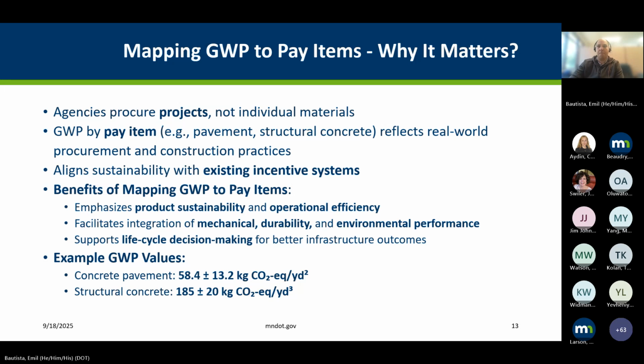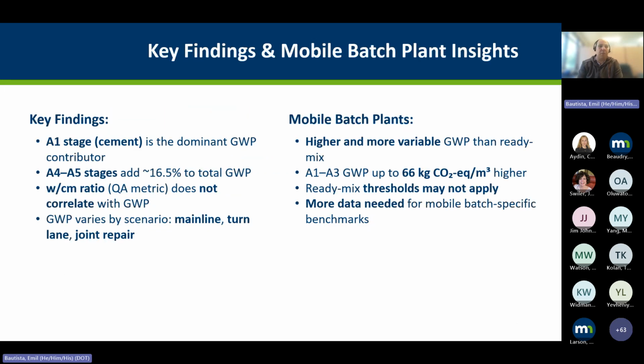Some of the key findings in this report, and also some important mobile batch plant insights: at the A1 stage, the dominant factor is the cement. Like I said before, we know that it's worldwide. A4 and A5 stages can add around 17% to the total global warming potential. They did not find any correlation between water cement ratio and GWP, and that's a very important correlation because it's a quality assurance measurement for us internally. And if I'm correct, we do have some incentive tied to water cement ratio requirements.